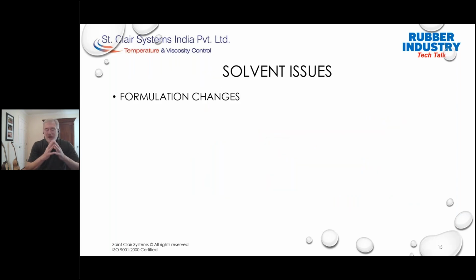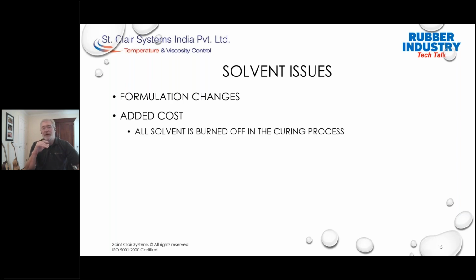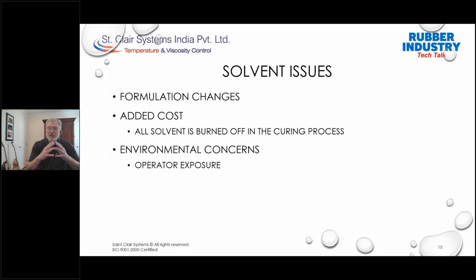But what many people don't think about is that adding solvent alters that carefully developed coating formulation that Parker Lord worked so hard to create. And the solvent creates many issues within the application process. Now, first, it represents excess cost because every drop of added solvent has to be driven off in the oven during the curing process. And in addition to the environmental concerns, it also represents a risk to our operators.